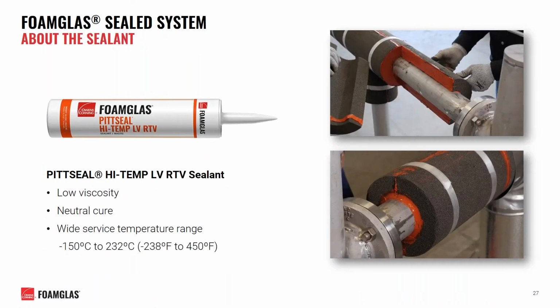A key component to the FOAMGLAS Sealed System is our proprietary PITTSEAL high temp LV RTV sealant. This sealant is specially formulated to be a low viscosity, which enables it to efficiently spread and seal all joints within the system. It neutral cures to an elastomeric solid at room temperature, does not contribute to corrosion, and boasts a wide service temperature range from -238 to positive 450 degrees Fahrenheit.